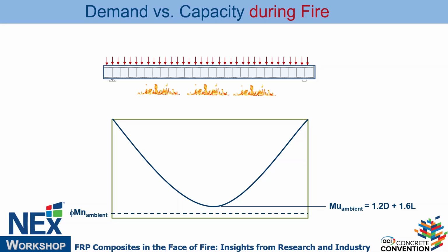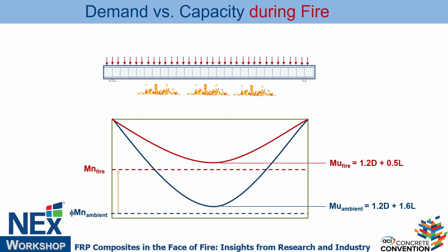What happens during fire is that, as we said, the temperature rises. I lose, could be some concrete section, but more important for flexure, the steel. The steel temperature will rise, its yield strength will drop, so my capacity may drop, right? However, I do not compare to the factored load, I compare to a different, lower load combination. So as long as my reduced capacity is greater than this load combination due to fire that we went over, and I have the benefit of its reduced load, and also I have no reduction on the material, that's another gain. This means I have adequate fire rating, right?